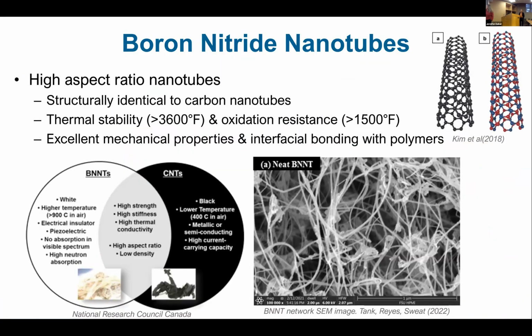In air, you have 400 degrees C temperature. This is a little higher than that sometimes, up to 800, but this is over 900 degrees C in air. So that's potentially a better opportunity for additive manufacturing. CNTs typically have a higher aspect ratio. That might be beneficial. There's different properties, depending on what kind of final property you want. If you want those additional B2O3 crystals to act as a structural char or something like that, the CNTs would decompose into amorphous carbon. So it just depends on the structure that you want.